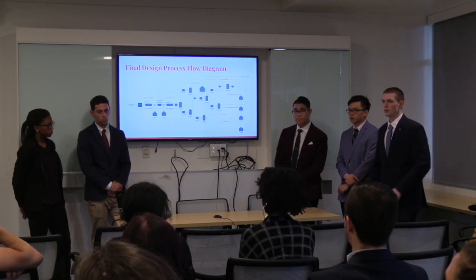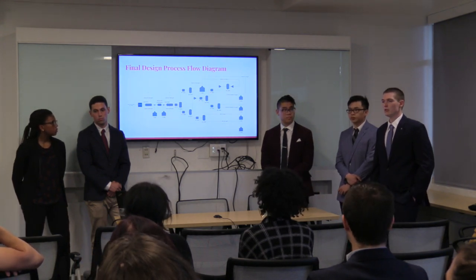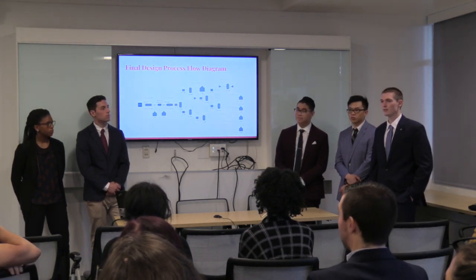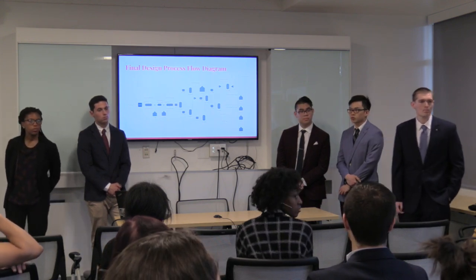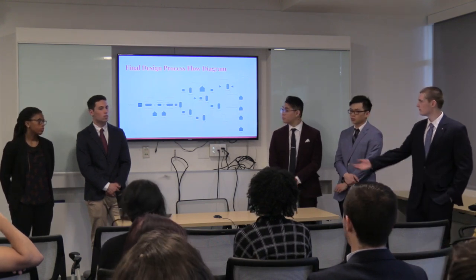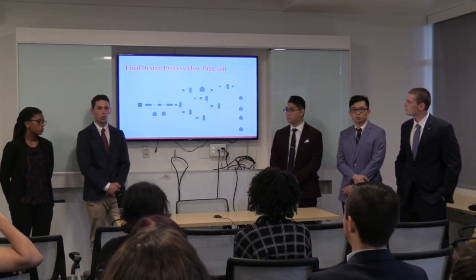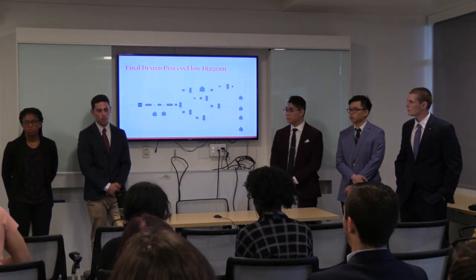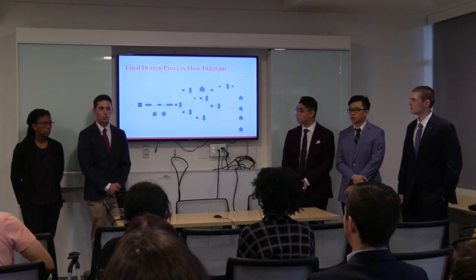System-wise. So you're going to use what catalyst, did you say? It's silicalite, which is a medium pore zeolite catalyst. Yes. And did you look into the regeneration process for the catalyst, what that requires in terms of chemicals and time? Yeah, it's basically just a hydrogen peroxide wash. The catalyst loses its activity just by having the pores clogged with material. So for the most part, you can just wash out with hydrogen peroxide, it'll restore its activity. We still accounted to replace it after every, I think it was bi-monthly or something.